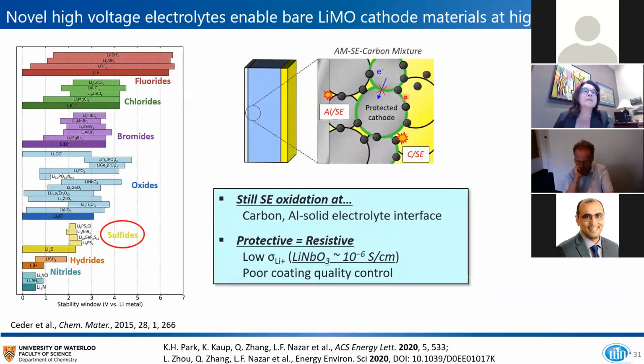And the reason for that is that the cathodes, if you don't want to use sulfides, and sulfides are fine because that's sort of its limit of oxidation potential. But if you want to use higher potential materials to get higher energy density, these lithium metal oxides, you actually have to protect the surface of these materials to protect the electrolyte from being oxidized at that potential, because these operate at about 4 volts and above. And the other problem is that the electrolyte will also be oxidized by the carbon and at the surface of the current collector. So the sulfides are fundamentally not ideal for catholyte formulations because of that low oxidation potential.